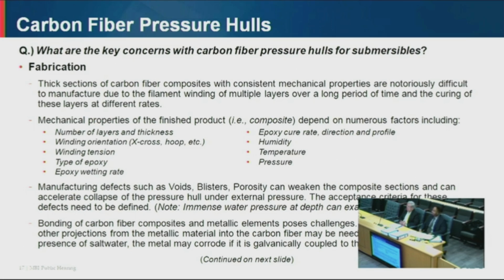The next thing that's challenging is bonding of carbon fiber composites with metallic elements. Typically, if you bond a carbon fiber composite with a metal, you'll have projections coming out of the metal, typically fins, and these projections go into the carbon fiber composite and help in getting better adhesion. So in addition to applying an adhesive, you have to have co-lamination. That ensures better adhesion between the carbon fiber composite and the metallic element. Now, galvanic corrosion is an important consideration here, because if the metal comes in contact with the carbon fiber strands in the presence of seawater, you can have galvanic corrosion. This typically occurs in steels and aluminum, and that can cause corrosion of the metallic members. Okay. Next slide, please.